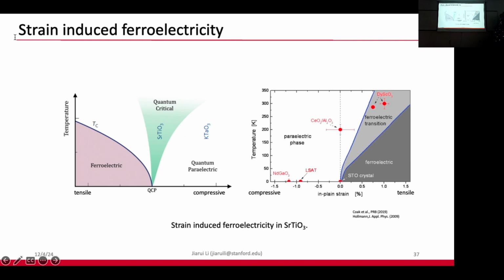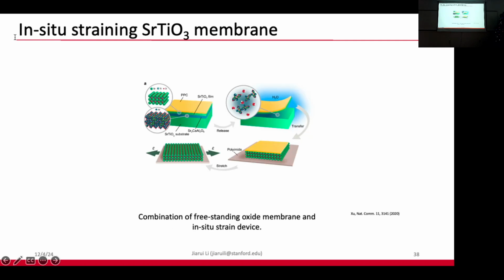And so we want to attack this problem from another point of view, from the material side. So by using this epitaxial thin film synthesis, we use a so-called freestanding oxide membrane technique. So we synthesize a stack of oxide materials with an intermediate water-soluble layer, strontium aluminate. So we have a substrate, we epitaxially grow another layer of strontium aluminate, and we grow our strontium titanate film on top.